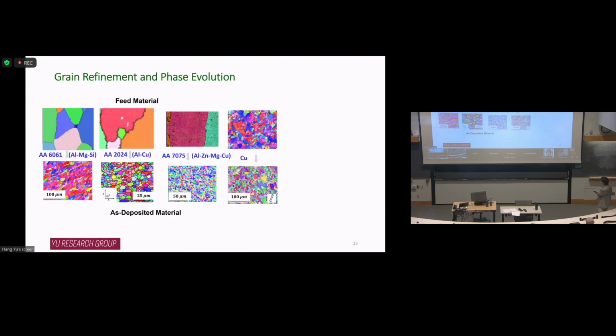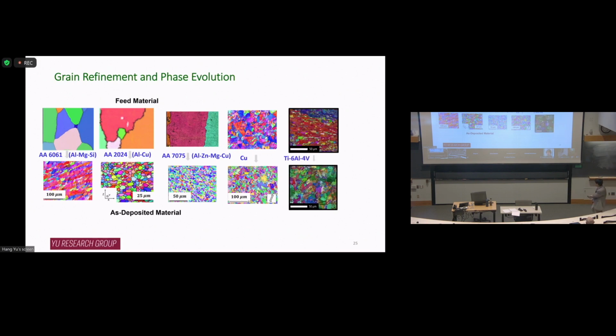For copper, we see signs of discontinuous recrystallization. And for titanium alloy, like Ti64, it's more complicated because the deposition temperature is above the beta transus. So essentially, the material transforms to beta phase, and you have dynamic recrystallization to form equiaxed beta grains. And during cooling, the alpha phase will form inside the prior beta grains. Eventually, you get this lamellar structure. Okay? But generally, you get some phase evolution or grain refinement in the deposited material.